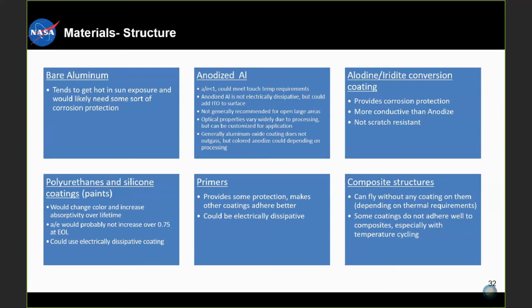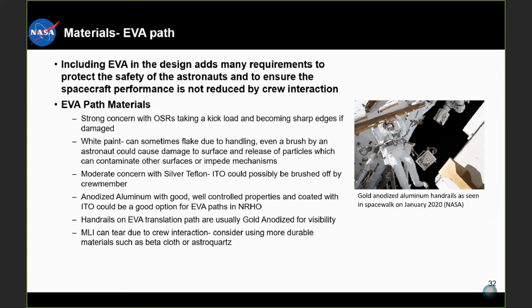The next one is polyurethanes and silicone coatings or paints. These would end up changing color and increasing absorptivity over the lifetime, though. The absorptivity to emissivity ratio would probably not increase over 0.75 at end of life. Again, on this one, you could use an electrically dissipative coating. The next material is primers. Primers are used to provide some protection. They do make other coatings adhere better, and again, could be electrically dissipative. And finally, we have composite structures. These can fly without any coating on them, obviously depending on thermal requirements. Some coatings don't really adhere well to the composites though, especially with temperature cycling.